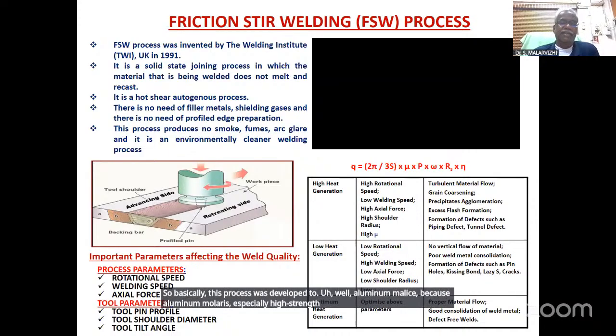This process was initially invented by The Welding Institute, TWI, UK, in 1991, and it was a patented process till 2001. After 2001, many people started working on this process. Basically, it was developed to weld aluminum alloys, because high-strength aluminum alloys are challenging to weld by MIG or TIG welding because of hot cracking, porosity formation, alloy segregation, and partially melted zone. These are the problems that normally occur in the fusion welding of high-strength aluminum alloys. So this process was developed for welding aluminum alloys.